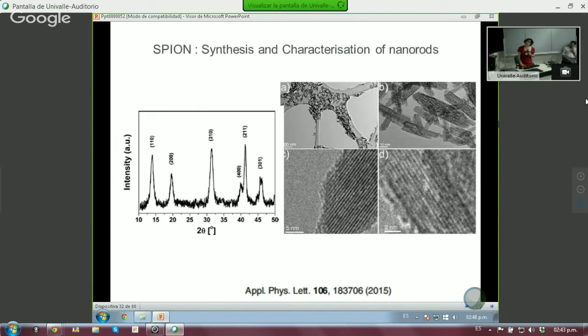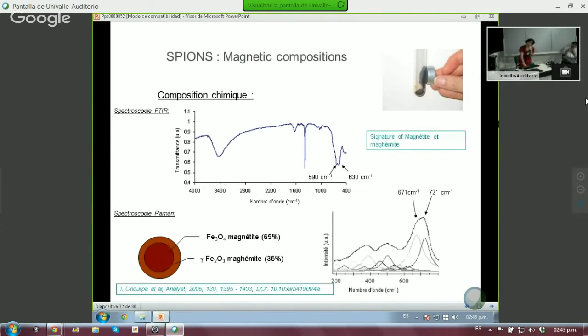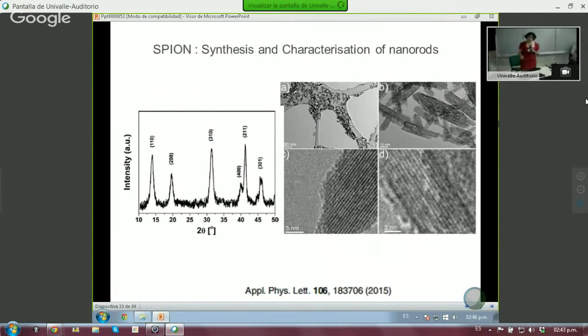Anyway, so what we constructed here were just simple nanoparticles. I'd like to show you something we just published recently. Here we used nanorods, because there are some procedures which become much more efficient if one changes the shape of the nanoparticles. So in this case, we used nanorods, and as you can see here, there is the XRD, and then you have the TEM pictures. And this is another alternative to spherical nanoparticles.